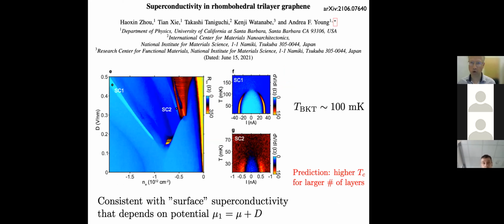Now, experimental progress on the possibility of superconductivity in this system: there has been quite recent work on this by the group of Andrea Young. They studied rhombohedrally stacked trilayer graphene, and this is the phase diagram of the linear resistance with respect to the charge density and an internal electric field between the layers. They find these superconducting domes, which are quite interesting. The only thing is that this is nowhere near room temperature superconductivity.